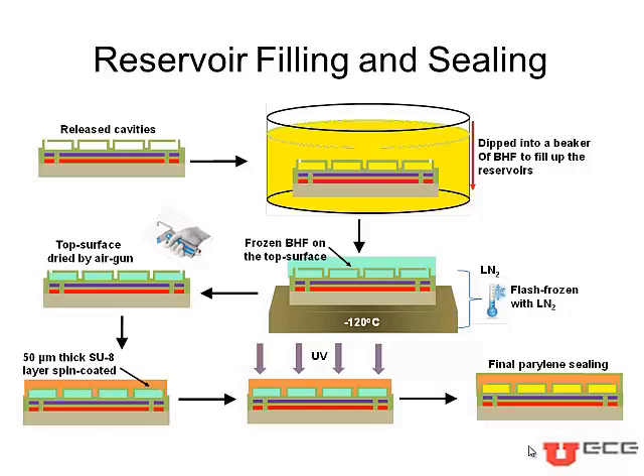Next, we spin coat a 50 micron thick layer of SU8 photoresist and then immediately expose it to UV radiation to harden it. This procedure completely seals the frozen BHF inside the reservoir cavity. Then a final layer of parylene is deposited to encapsulate the entire device.